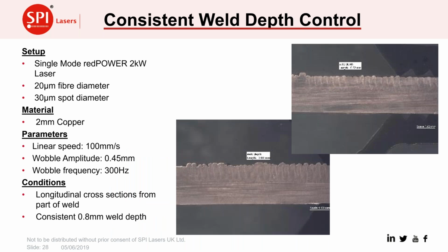We also find that despite the oscillation motion of the laser, the weld depth is pretty consistent. And this is a bead on plate weld. I'm sorry, the measurements seem to have got a little bit messed up here. But it's a bead on plate measurement, and we're looking at the top rough bit of the weld, on the top third of those two photographs, which were different 10 millimeter sections taken from a long weld, where we were welding this 2 millimeter thick piece of copper, just putting a bead on plate there. Across the whole length, the weld depth in this case was about 0.8 millimeters. These are longitudinal sections, and we got a very consistent depth across the length of the weld.